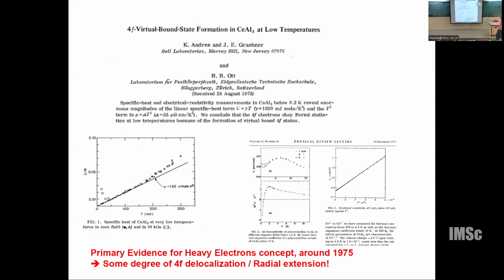Now, when the research was going on in the 1970s and 80s, people found much more exotic behavior. For example, cerium aluminum 3, the first compound where they found that if you measure heat capacity as a function of temperature, there's a linear term. The heat capacity of simple metals contains two terms. One is a linear term, gamma T. Gamma is an electronic coefficient related to density of states. The second term is a lattice term, beta T cubed.